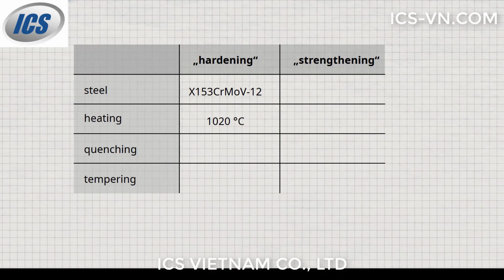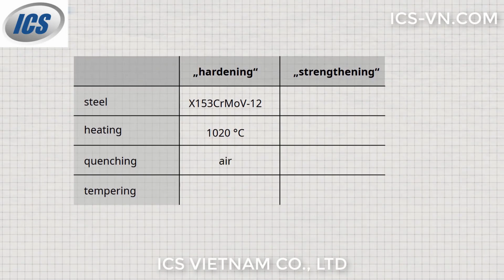Then this high alloy steel is quenched in air. After quenching, tempering takes place at around 300 degrees Celsius.